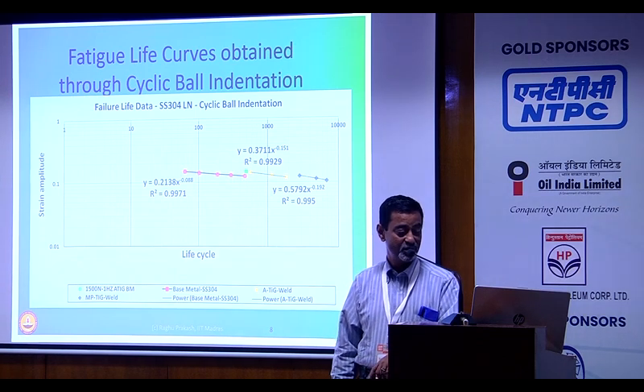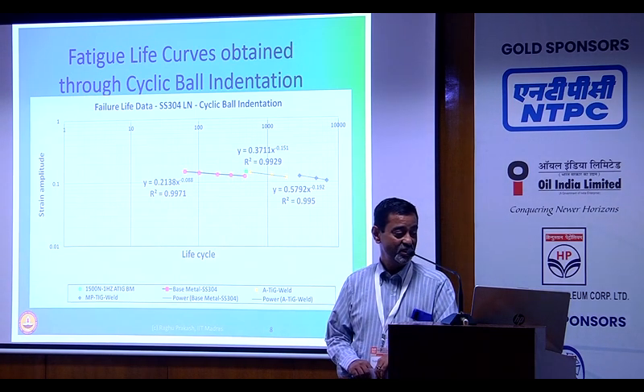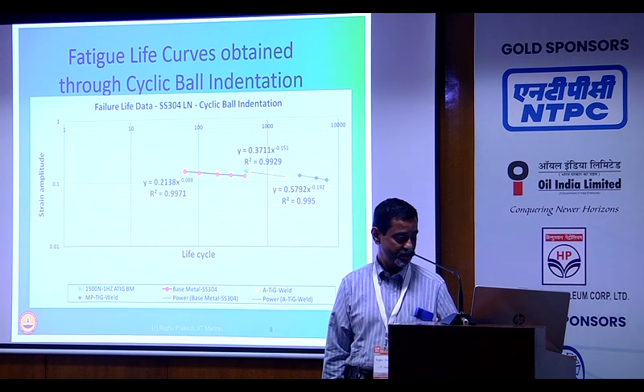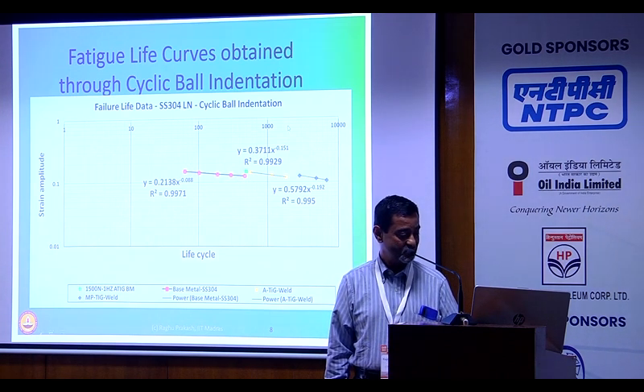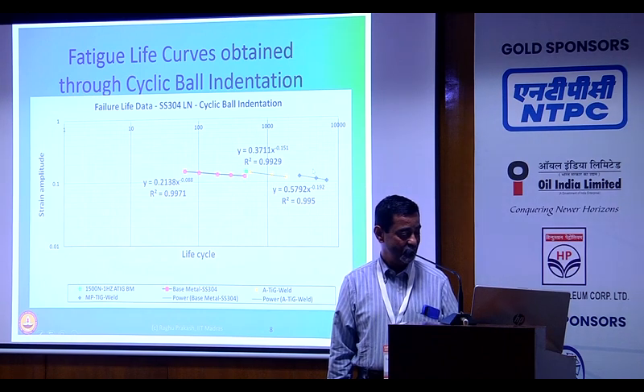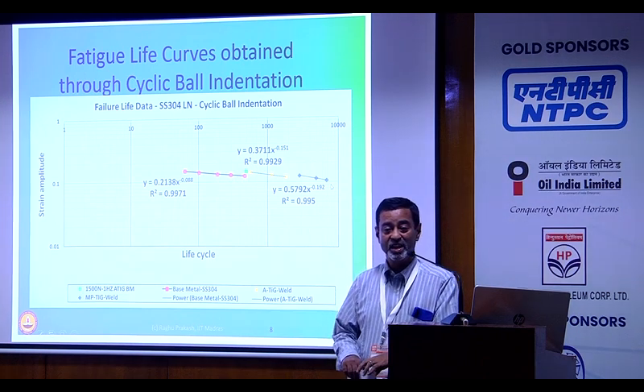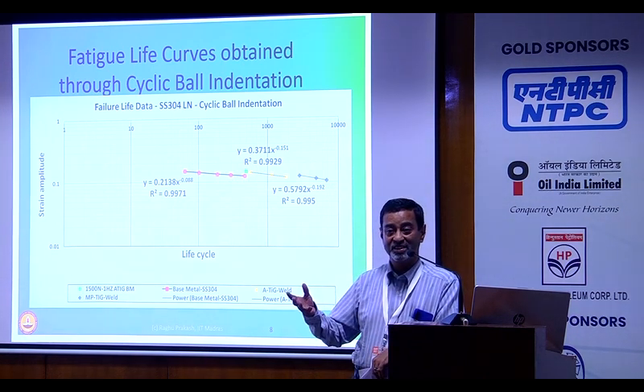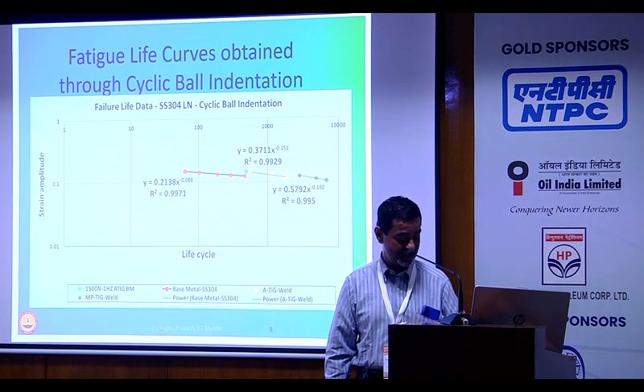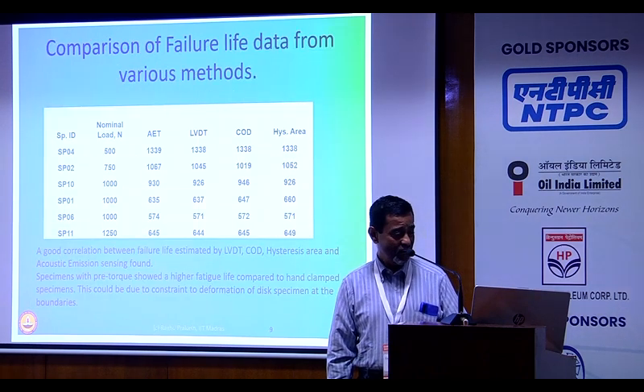To give you a glimpse of the results, you can see here the fatigue life curves obtained through cyclic ball indentation, where you can see the base metal shown over here, and you will also see the data for a welded region, different kinds of weldments, and how it changes. Which means that if I have this data, I can go and correct. If I have a welded region where I want to predict the failure, I'll use appropriate strain life curves rather than having to use the pristine material data.